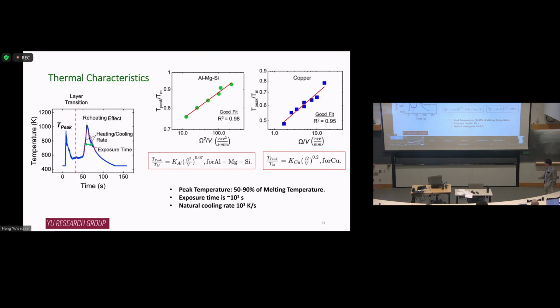The natural cooling rate is on the order of 10 to the 1 Kelvin per second. So it's pretty slow cooling compared to the laser-based additive process, which can easily give you like 1,000 or 10,000 Kelvin per second, right? Of course, we can increase this by some active cooling mechanisms.